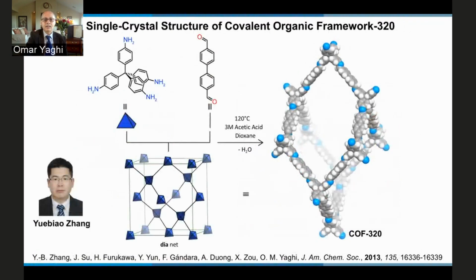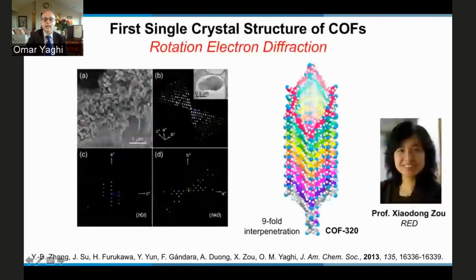We can make the expanded version of that, again under the same conditions, except with a little bit more acetic acid. The crystal structure of this COF was determined from electron diffraction, in collaboration with Professor Xiaodong Zou, University of Stockholm, and it revealed that the structure is 9-fold interpenetrated. But this was the very first time one could get a single crystal structure of a COF.